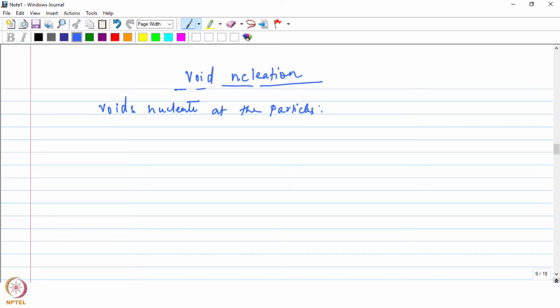So let's talk about the first stage, that is void nucleation. So here we have particles dispersed in the matrix, and it has been shown that the voids nucleate at the particles. Although void nucleation in the matrix has also been suggested, by in situ experiments it has been shown that voids actually nucleate near the particles. Okay. And in particle reinforced composites, there are two modes of void nucleation.